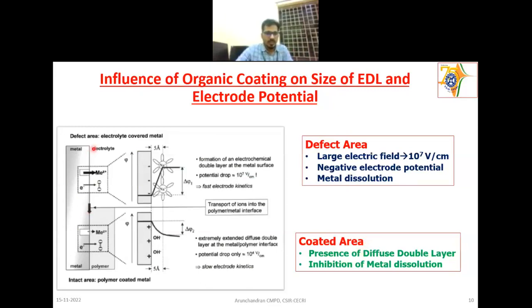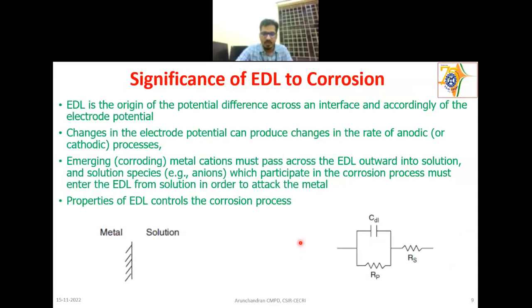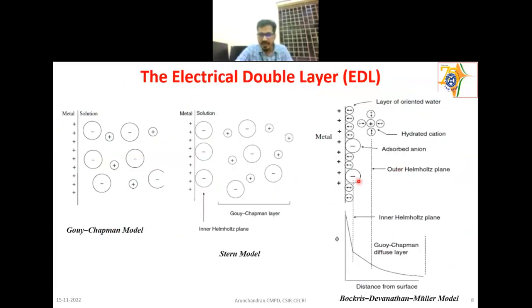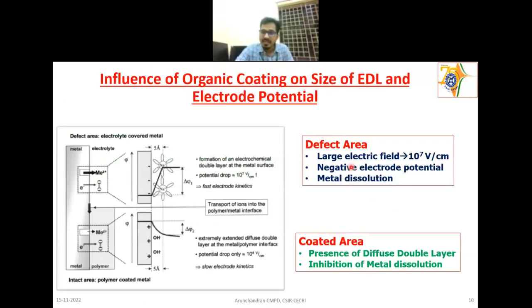So in this figure, you can see the first image, this is a metal and electrolyte. Here there is no coating, but here there is a coating. So here you can see the large electric field. In this small area, the electric field will be of the range of 10^7 V per centimeter, because it is 1 volt only, but the region is very narrow, about 1 angstrom only. That's why you have a very high electric field.